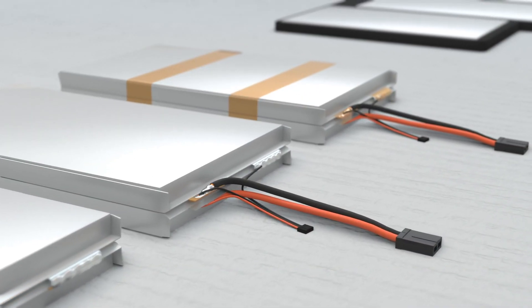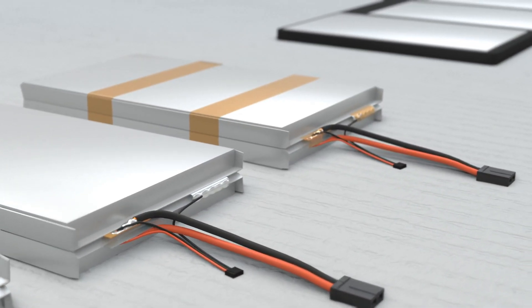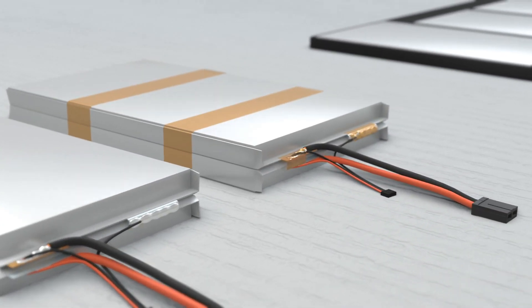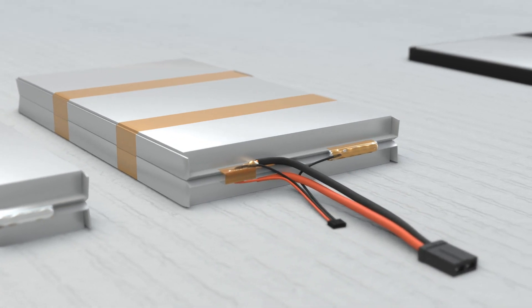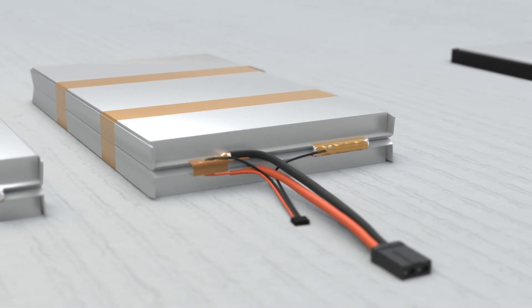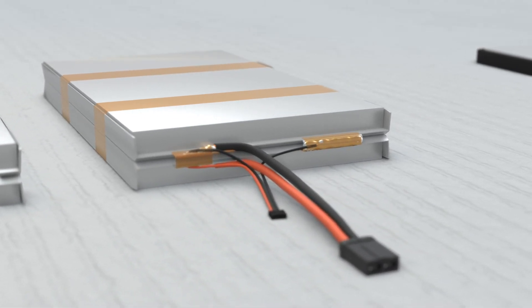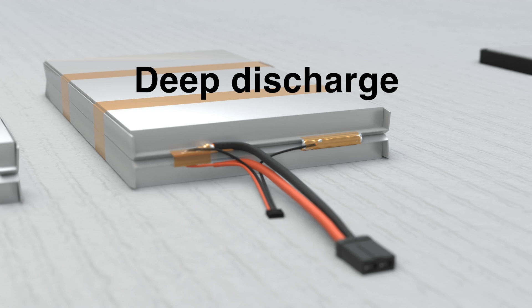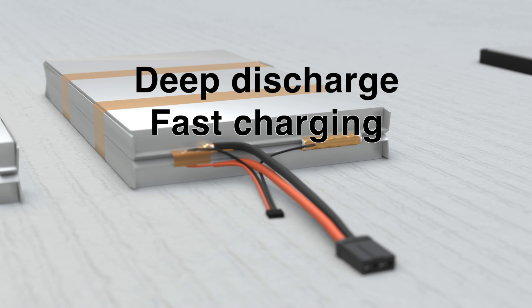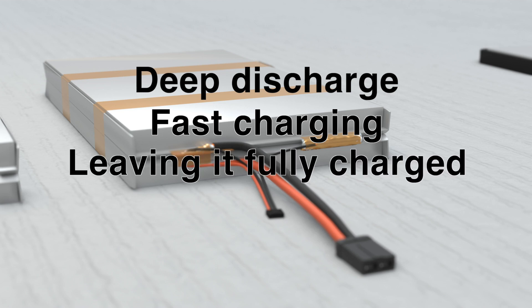From experience, after I've tested and cycled many lithium cells and many of them being LiPo type, there is one thing that really degrades and damages the cells. That is deep discharge, to fully discharge the battery. Other factors are fast charging and leaving them fully charged for a longer period of time. And of course, heat.